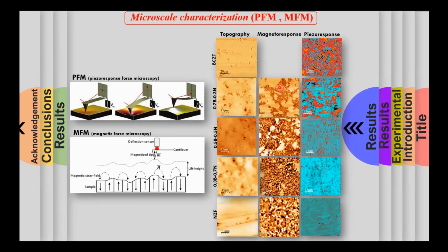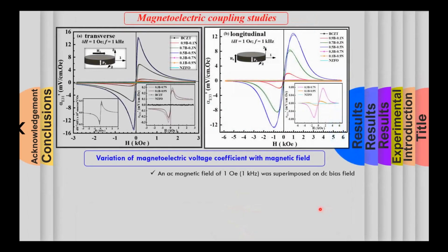When we compared the MFM images with the PFM, it was revealed that the magnetically active regions do not show any piezoelectric activity and vice versa. So this implies that a sharp interface separates the magnetic and the ferroelectric phase, and there is no apparent interdiffusion. Magnetoelectric coupling was studied